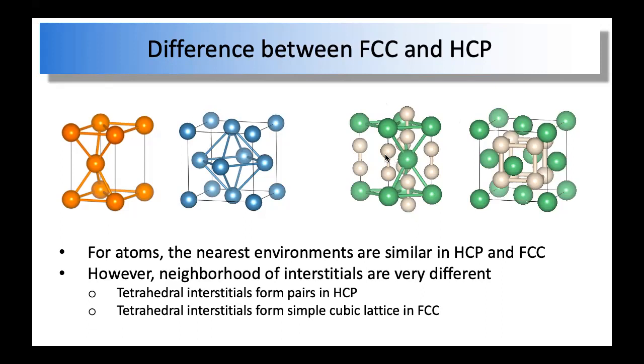So here are the tetrahedral interstitials of HCP and FCC, and you can see the tetrahedral interstitials in FCC form a perfect simple cubic lattice. Okay, so these are the diamond structure occupation, right? The quarter, right? And you have eight of these interstitial sites in one conventional FCC unit, and they form a simple cubic lattice. However, if you look at HCP, they form pairs. So the two tetrahedral sites form a pair.